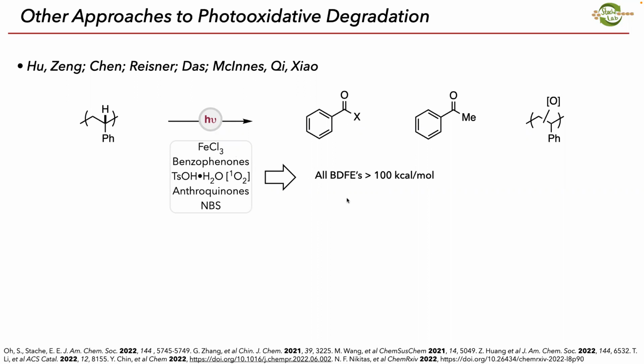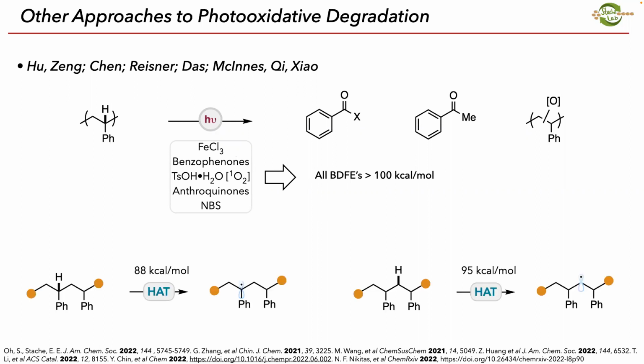And what that means is that we don't get any selectivity. That's a very high number. And so that can abstract any of the CH bonds in polystyrene. And so, right, there's a possibility of abstracting this tertiary CH bond, which has a bond dissociation energy of 88 kcals per mole, which is much less than 100. So we can easily use any of these reagents to abstract that one. But similarly, the secondary CH bond is also less than 100 kcals per mole, and so we can easily abstract that one. And so we don't get any selectivity between those 2 CH bonds.